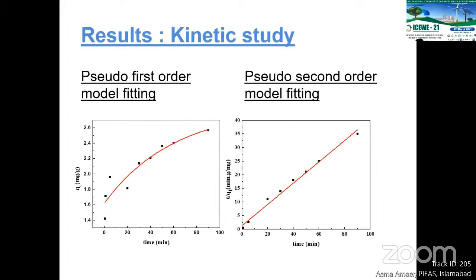Next is the kinetic study. Kinetics was studied through pseudo first order and pseudo second order models, and we can see that it was well fitted by the pseudo second order model, and the correlation factor was about 0.988. What it tells us is about the chemisorption of lead ions, meaning there occurs a chemical bond between lead ions and alumina, and when there is a chemical bonding between lead ions and alumina, regeneration becomes very difficult in that case.